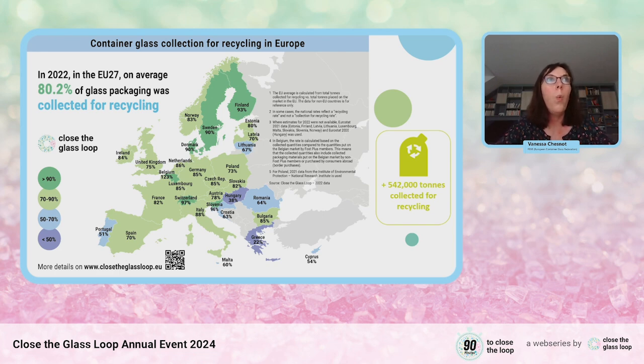Then in terms of the trends, what this map doesn't tell you, if we just focus on the EU average and the ratio, is that we have a numerator, we have a denominator. And what is notable is that despite the collection rate being stable, more glass packaging was collected in 2022 than ever before. So we have reached a record high level of 12.4 million tons collected in 2022. And this is an increase of about 542,000 tons over the previous year. And so what it means is that the amount of glass that was collected kept up with the significant increase in the amount of glass that was placed on the market. So around 4.5%. And this, of course, is a very positive trend in glass collection efforts across Europe.